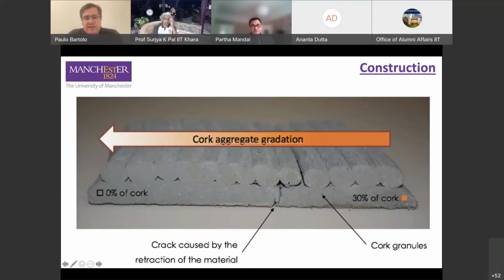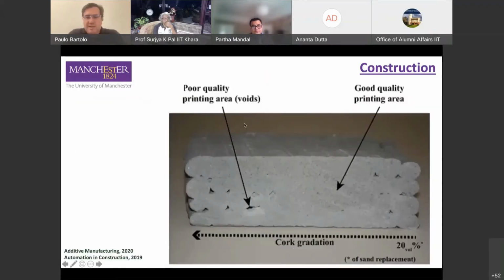So, as you can see, there are some cracks, some pores, and this was essentially due to the lack of process optimization. So we solve most of these problems by optimizing processing conditions. This is another example of another structure. And again, we were able to create a functional graded structure by changing the amount of cork present in the